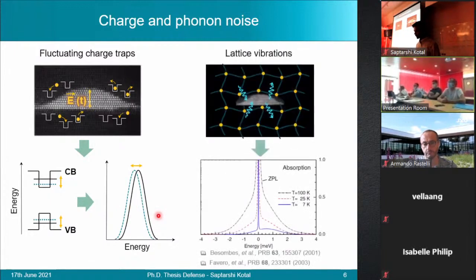When you have charge noise, the fluctuation of charges around the quantum dot results in a fluctuating electric field at the level of the quantum dot, which makes the optical transition energy of the quantum dot fluctuate, which translates into a broadening of its emission spectrum. Lattice vibrations, on the other hand, act on the quantum dot through the interaction with acoustic phonons. These phonon modes generate strain on the quantum dot, thus modifying the emission energy of the emitter through deformation potentials.